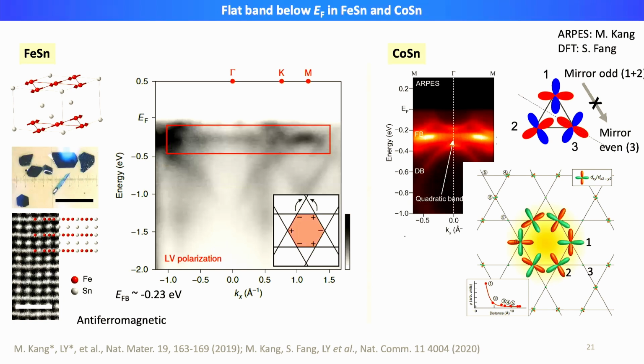Right. The point I wanted to make here is that although the model we started with was very simple, where we only considered isotropic hopping, even with incorporating realistic details, for instance the orbital degrees of freedom of the d electrons of cobalt, we still have the same frustrated hopping at play, and the flat band physics is still relevant, even though the starting point was very simple.